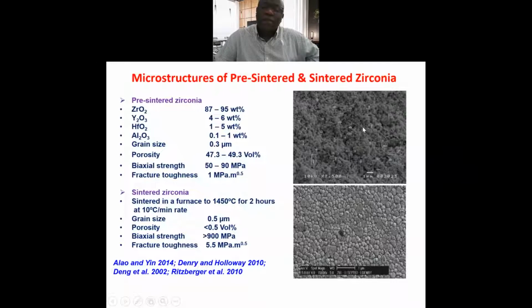When this presintered zirconia is sintered in a typical furnace to 1400 to 1450 degrees centigrade for 2 hours, at 10 degrees centigrade per minute heating and cooling rate, the grain size enlarges, which closes the porosity. You can see from 0.3 to 0.5, the porosity has reduced drastically, and the biaxial strength has improved, and fracture toughness also improves.